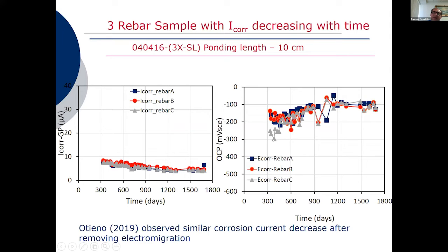You can see that each one of the rebar potentials tended to increase, and these values are versus calomel reference electrodes. If you want to convert them to copper sulfate, you subtract 75 millivolts, and that will give you the value versus the copper sulfate electrode. You can see that we are reaching almost 1,800 days of monitoring, and this period that I'm encircling with the cursor, you might or might not be able to see that, those last 450 days are the ones that were measured as part of this effort.